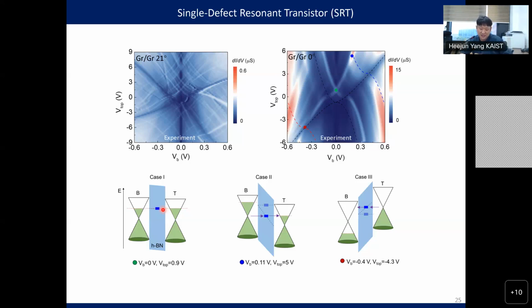So my interpretation of my data is like this. We have some series of defects in the hBN. And then somehow, by chance, we have a certain period, maybe 10 defects with a certain period. And if you do the Fourier transform, this period could be interpreted as momentum. Of course, we cannot allocate a certain defect series, but this was made naturally. But we have very few defect series with certain momentum.